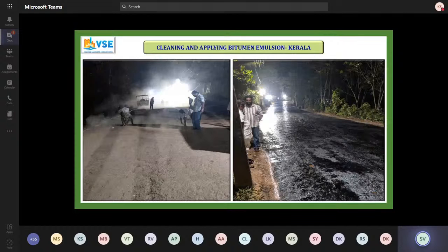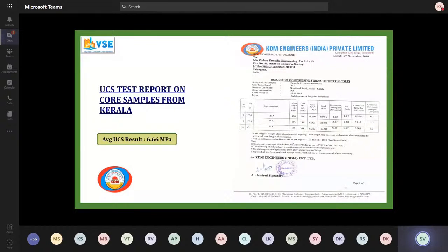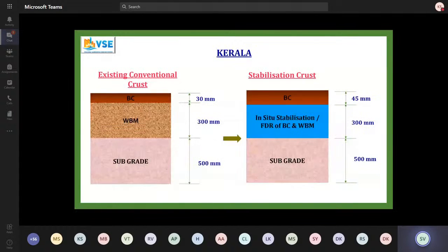Then we spray bitumen on top and go for the laying coat. In this particular road, traffic wasn't great, so we didn't go for any DBM. We went straight for the BT. We did this almost 2.5 years ago in Kerala, and it's still holding very well. These are the cores again. You can see the entire depth of existing WBM was there. For the entire depth we went for stabilization of 300 and then went for a layer of BC on top.